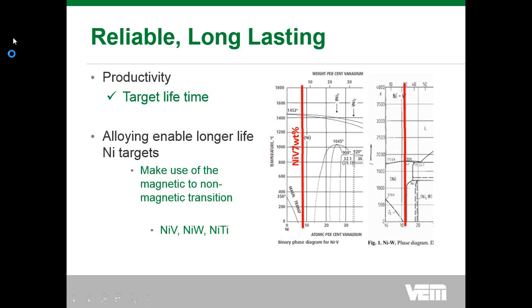The problem is that when you sputter, the sputtering process tends to undercut that lamellar structure, leading to it breaking off and leading to the generation of particles in the film. Again, as I said, if I control time and temperature and pressure, I can actually produce that same alloy, eliminating the issue of this beta-Ti tungsten formation.